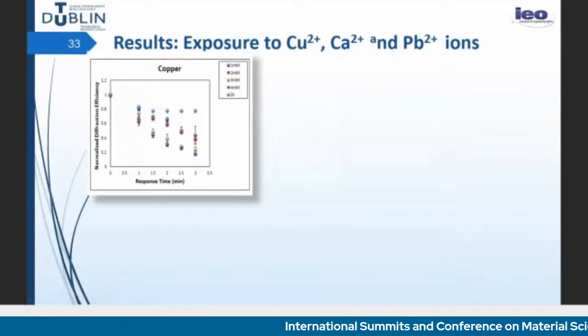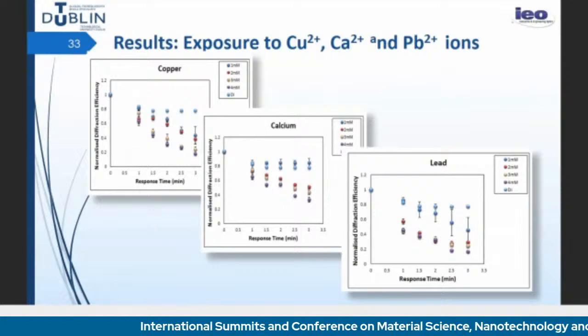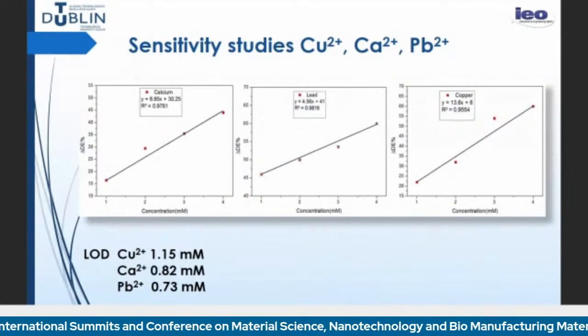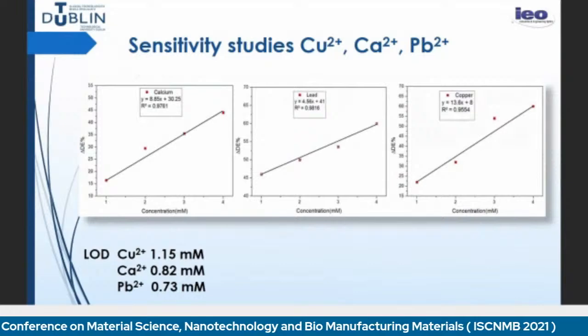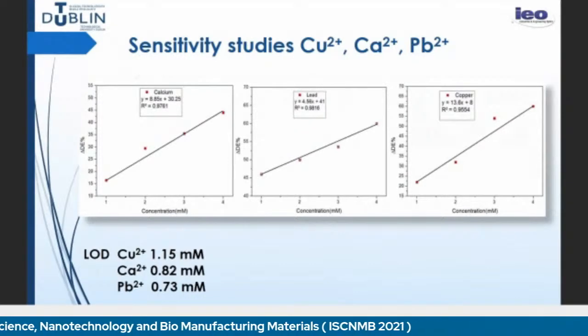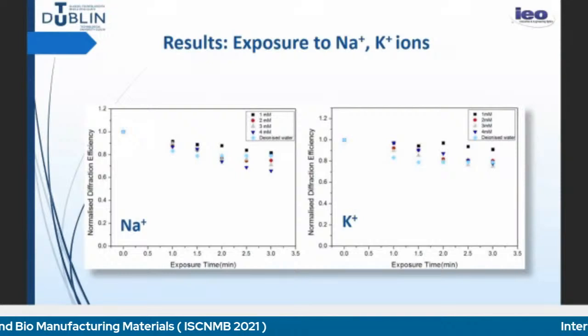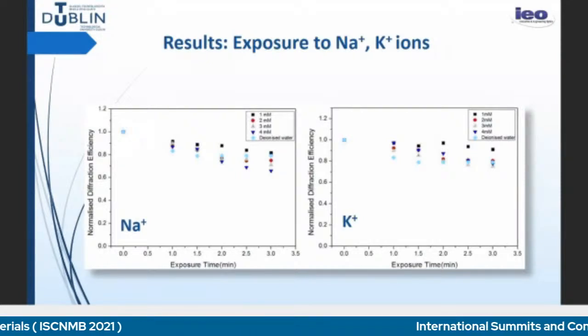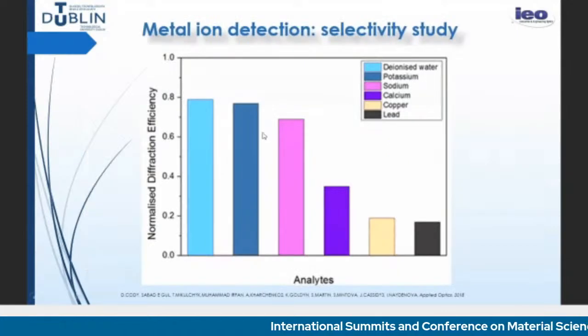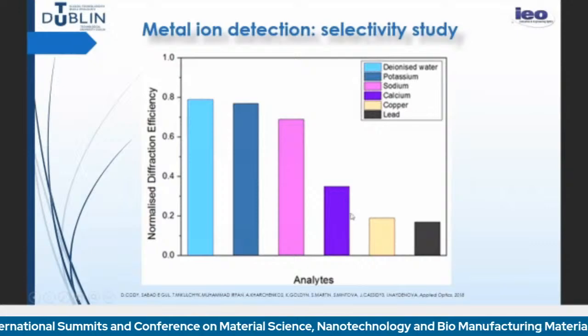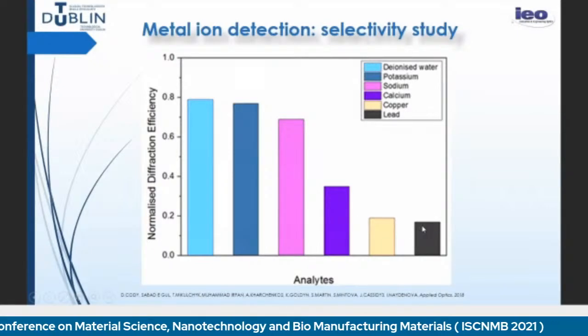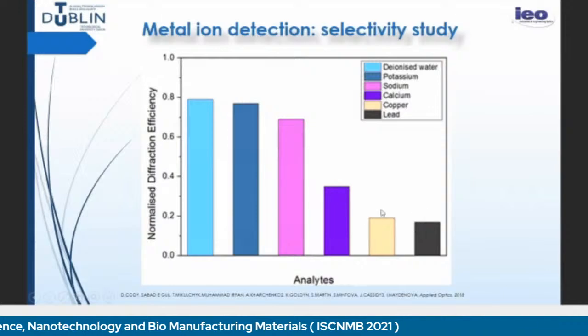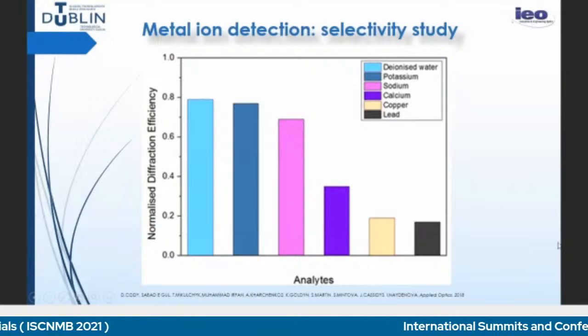We have done the same experiment with copper, with calcium and lead, and these are the limits of detection for these materials, being the lowest for the lead. So we have also exposed them to sodium and potassium ions, much smaller response. And here they are all compared together. So this is deionized water, potassium and sodium, much smaller response, and significant response for dications. So practically we can detect some metal dications in water, but we can't distinguish between them yet. So the selectivity is still an issue.